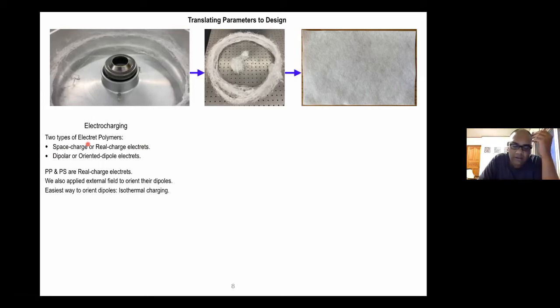So the material itself, the polymer molecules themselves, have dangling ions at their periphery, which give basically a static electric field to the material once you fabricate it. Or you can take a polymeric non-woven polymer fabric and apply an external field to orient the dipoles within the polymer material. There are several ways to do it. One common way we know is triboelectric charging, where you take two dissimilar fabrics and rub them together until one of them acquires a positive charge and the other acquires a negative charge.